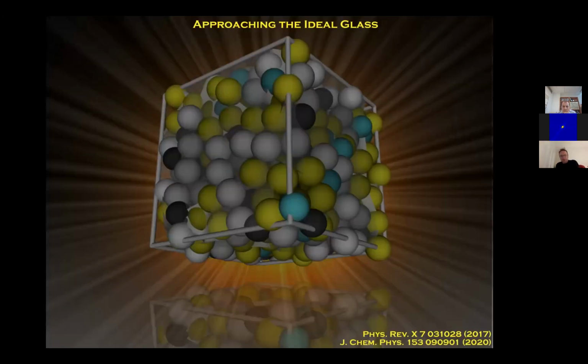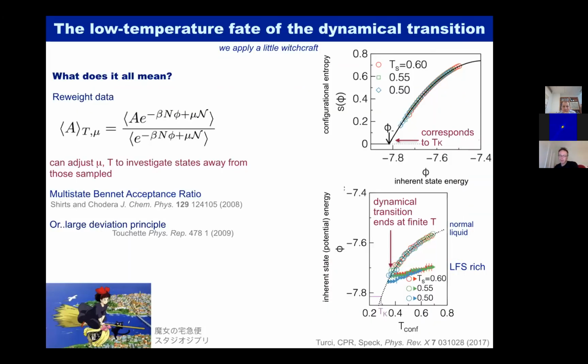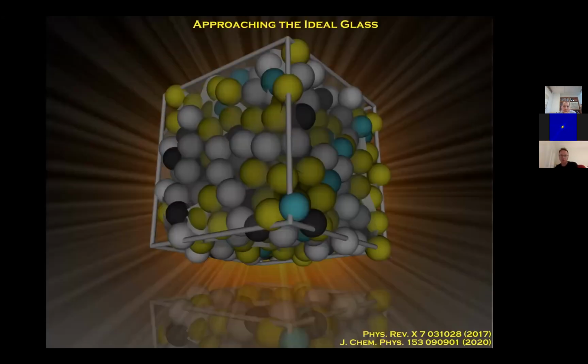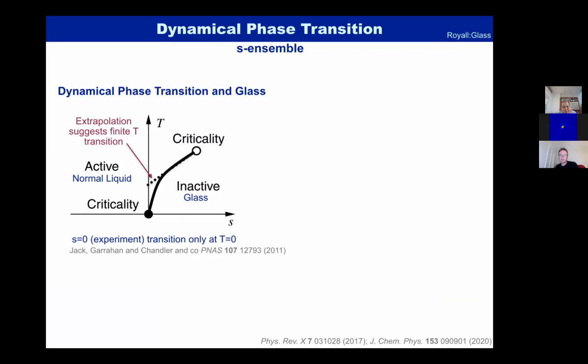What we have done, though, is to use this method to make configurations very close to the ideal glass. If I just go up, the Kauzmann temperature is shown on the bottom right, and we have generated data at temperatures very close to the Kauzmann temperature. And so we are able to say that this is at least close to the ideal glass, and this is what it should look like. Okay, but let me get back to the story.